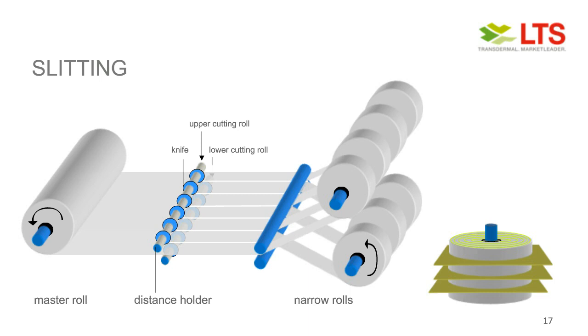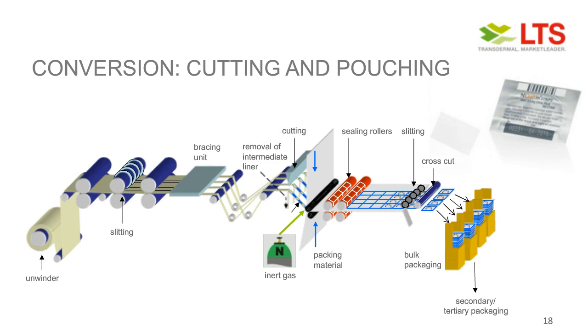So the last step, the conversion step, is where we make the single finished product out of it. So we start with unwinding of the narrow rolls. Here they are slit into several lines, several rows of individual film strips, and they are cut at the next step and then transferred into the packaging material, and afterwards these different pouches are individualized just by cutting, for example, here, and packaged in a bulk container at the end. Here we are packaging each individual film in one single pouch. As you can see here in the picture on the upper right, there's one film strip in one pouch, one sachet at the end of the day.